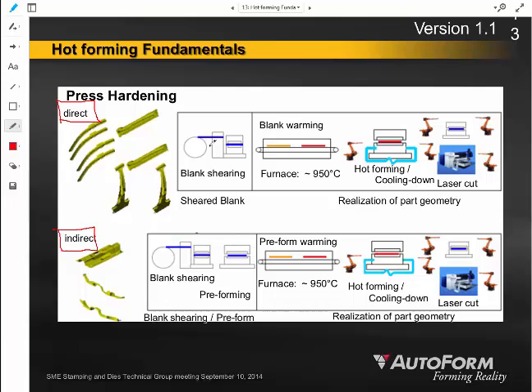Direct hot forming starts by taking the coil of material, unrolling it, creating your blank, taking that flat blank and passing it through a furnace to heat it up very uniformly to a temperature around 950 degrees Celsius, loading it into the stamping die, and inside of the die not only deforming the material, but as we're deforming it, also cooling it and quenching it down to ambient temperature, right?